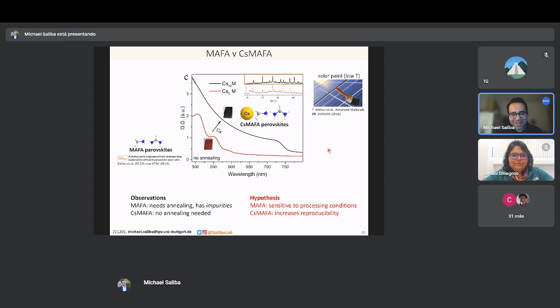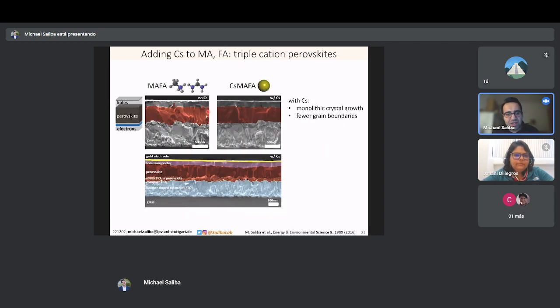And here you see also the cross-section of these double cation perovskites. Not only do they form the final phase after annealing, but also their grain structure is very different as well. The grains are ragged. They are stacked on top of each other. You have internal grain boundaries. So it's a bit of a mess, actually. Whereas when cesium is used here, you see it in the zoom out much more clearly as well. You have so-called columnar growth, where the grain goes from top to bottom. Very similar maybe to multicrystalline silicon as well.